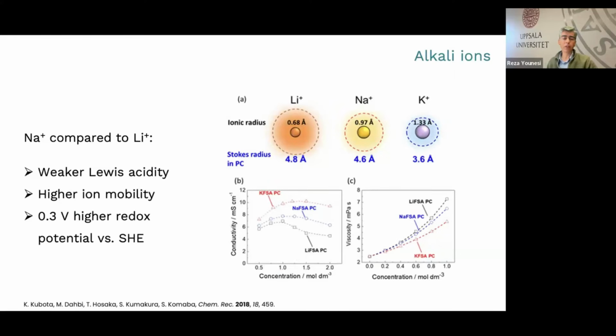There have been so many studies on understanding SEI in lithium-ion batteries, but to highlight an issue here: when we talk about sodium-ion batteries, not everything is exactly the same as in lithium-ion batteries. The reason is that there are differences between electrolytes and electrode materials used in lithium and sodium-ion batteries. As you see in these pictures, the ionic radius of sodium and lithium are different, which also leads to different solvation structures, different conductivity, and different viscosity, even if you use the same solvent and the same anion, just changing lithium to sodium.